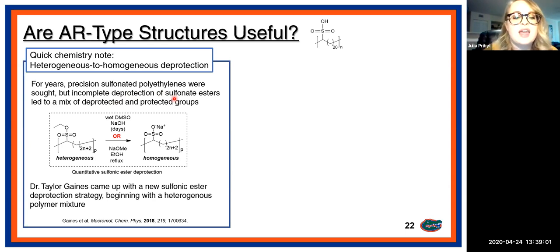And Dr. Taylor Gaines, who's a past graduate student in the Wagner group, came up with a new sulfonic ester deprotection strategy, which is really counterintuitive to most organic chemists, because we're always trained that deprotection chemistry should happen in a homogeneous mixture. So what he did, which was really clever, was he took the protected sulfonic ester and floated it on top of a solution of wet DMSO, and then threw in a couple of tablets of sodium hydroxide and left it for days.